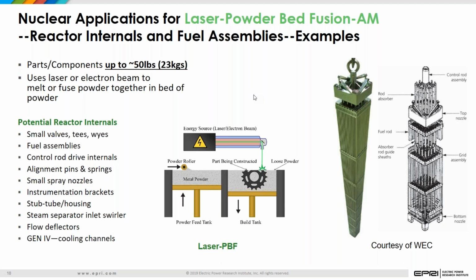The first one, laser powder bed fusion, typically is produced by utilizing a powder, wherein that powder is rolled over a component and a laser or electron beam source actually builds that component layer by layer. We think the components that we will see produced by this will include very small components, typically less than 50 pounds in size. I like to think of this as about the size of a microwave. If you can put something in a microwave, you could actually build it with this technology. So small valves, T's, Y's, a number of fuel assemblies and fuel handling equipment, things like that could be produced with this process.